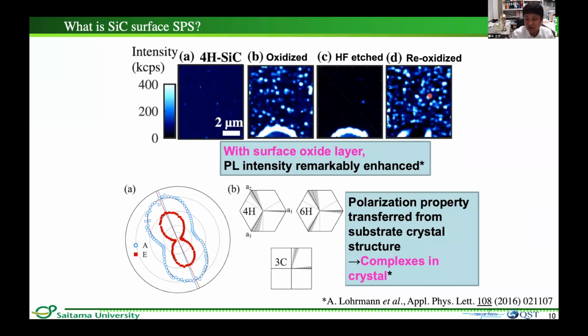Therefore, the oxide layer plays an important role to enhance PL intensity. In addition, polarization properties indicated the linear polarity, and their polar angle agreed with that of substrate crystalline orientations. Therefore, the surface SPS originates from complex defects existing inside the crystal.